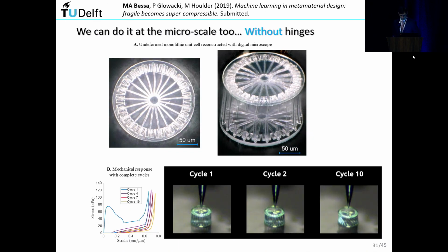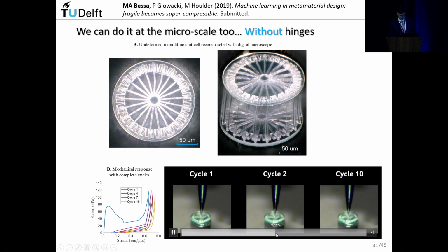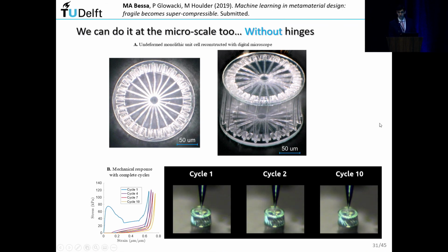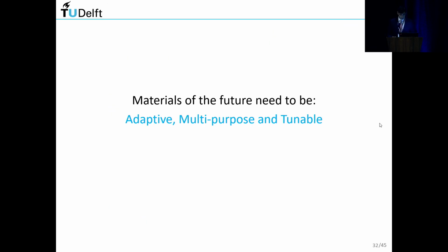But I have a little video for you that shows that the material is actually changing. I'm going to speed it up a little bit. So these are three different cycles. First cycle, second cycle, and tenth cycle. And you see that it goes down, and it comes back up in all these different cycles. Okay? And this is smaller than a grain of sand. The diameter of that ring is 200 microns. Okay, so we were very happy.